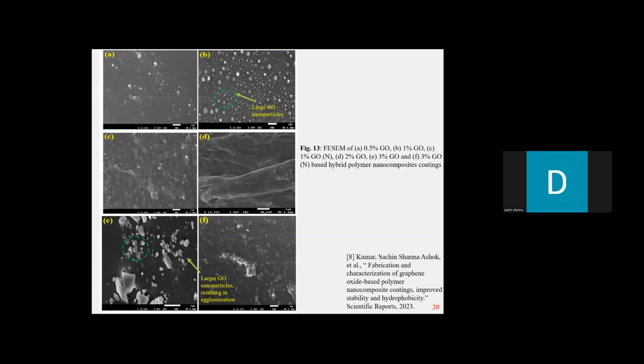So for B, which is representing the 1% GO without the influence of vacuum, we could easily see that there was presence of larger nanoparticle size. And it did not blend so well within the polymer matrix. For C, 1% GO N, fabricated with the influence of vacuum, the surface was pretty much uniform. It blended very well, and it was homogeneously dispersed within the polymer matrix.